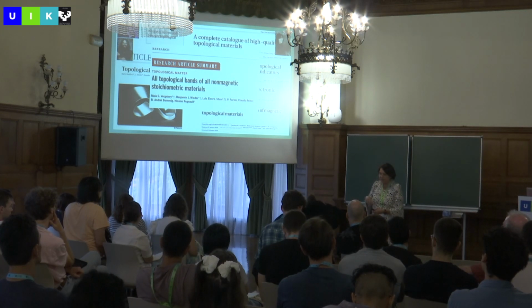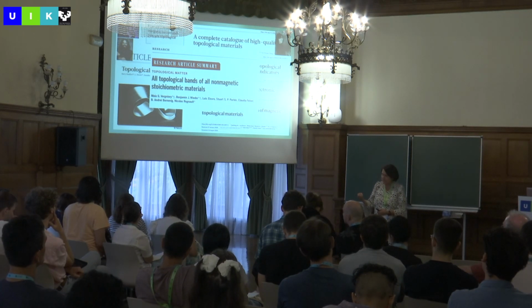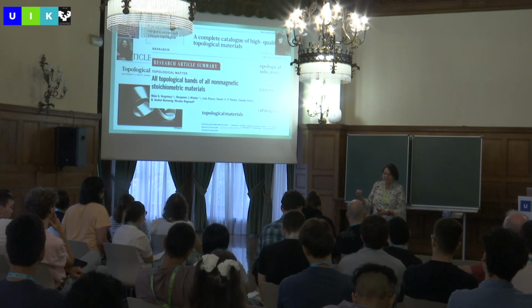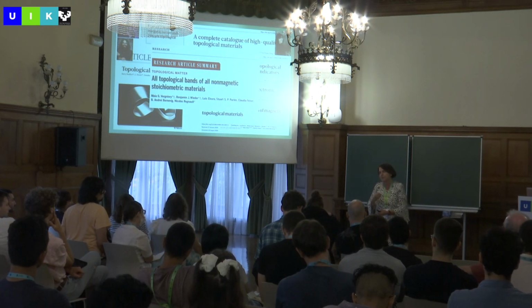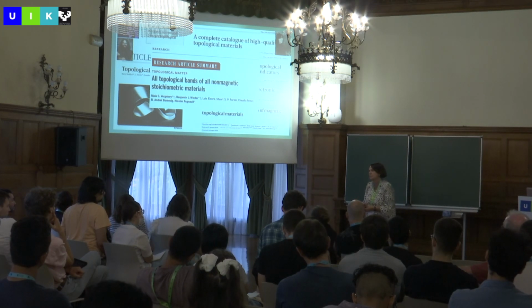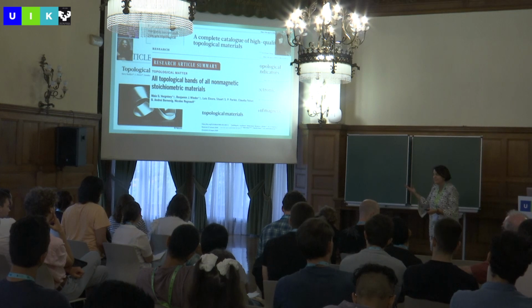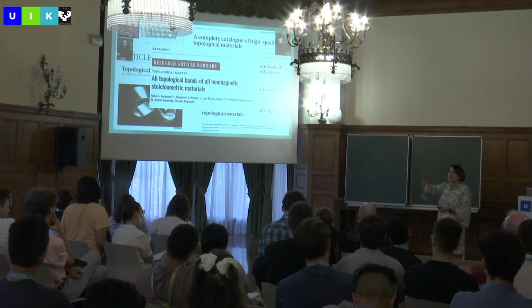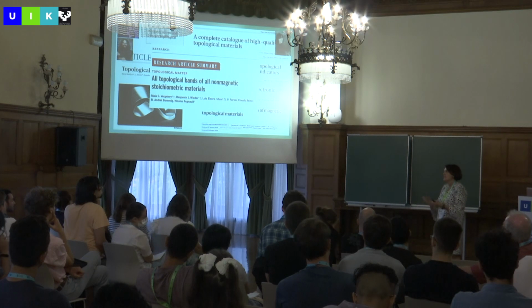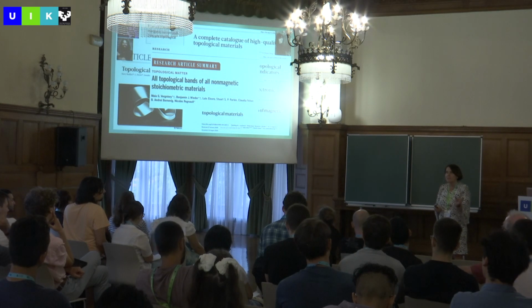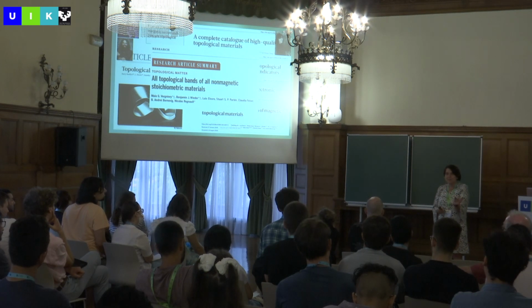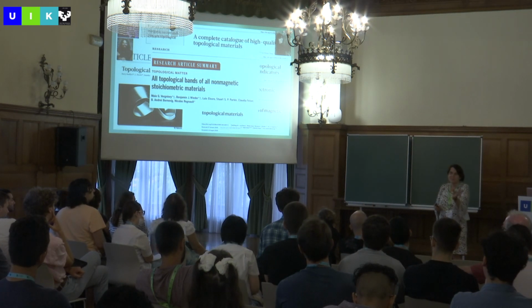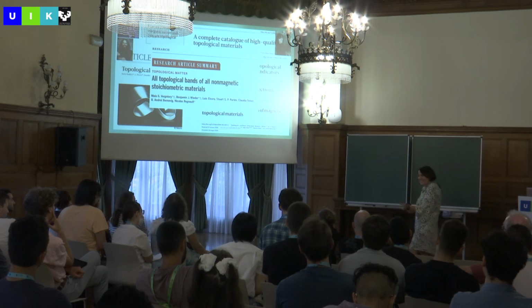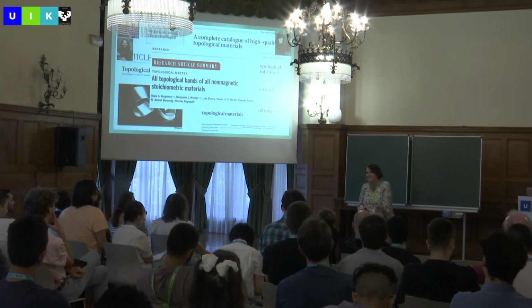Anyway, I still want to remind us that we really have to look for the features in the electronic structure, because I'm quite sure we will soon have more and more applications related to the topological properties. The nice thing is now we move a little bit, we dope a little bit around, and suddenly we see materials where we have mean free paths which are micrometers and millimeters long. So the mean free path, for example, in my tungsten phosphide 2, I don't advertise graphene, is larger than my crystal size.